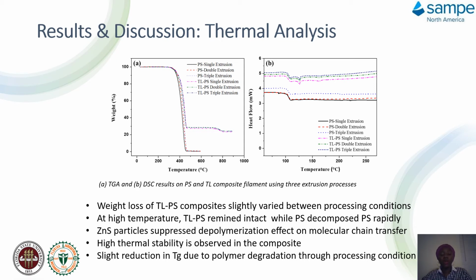And also the DSC confirmed that there is a higher temperature in the composite, which shows that the effect of the TL, which is a zinc sulfide crystal, in the composite suppresses the depolymerization effect on the molecular chain of the whole composite, and also makes it more thermally stable than the polystyrene without the TL inclusion.